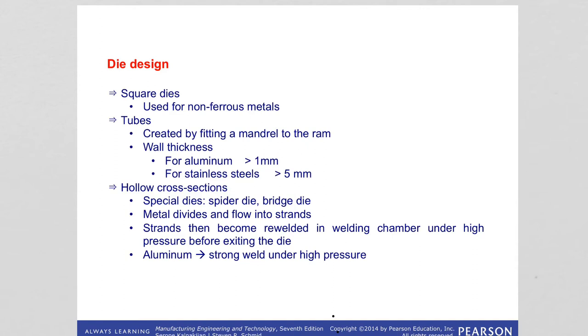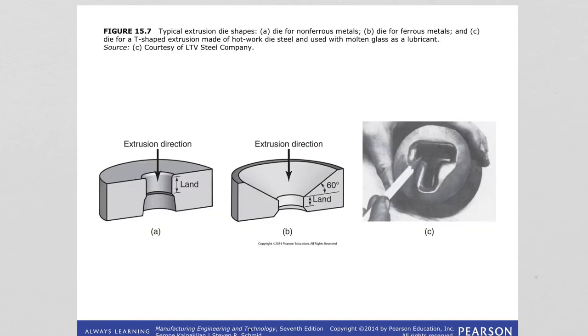Die design requires considerable experience. Square dies are used for extruding non-ferrous metals like aluminum, but they develop dead metal zones. Providing a die angle, as in image B, is more suitable for ferrous metals. Image C shows a T-shaped extrusion made of hot-work die steel.